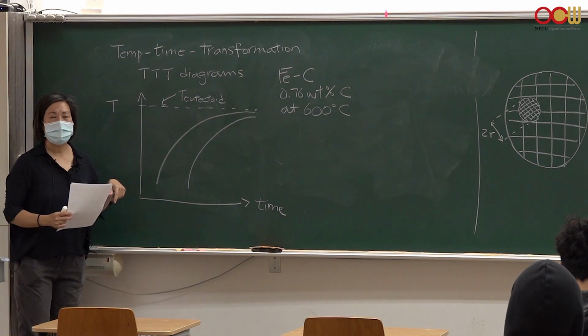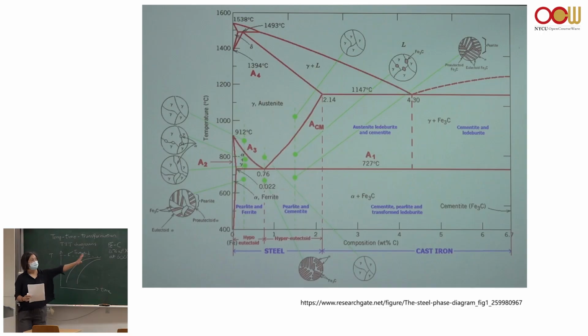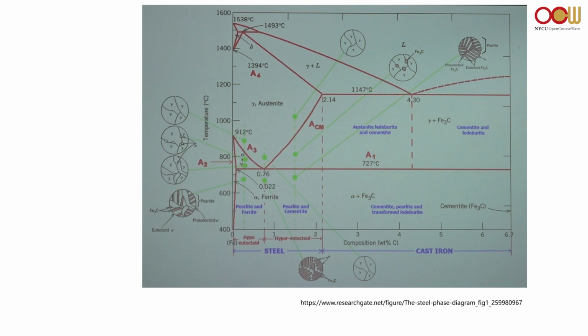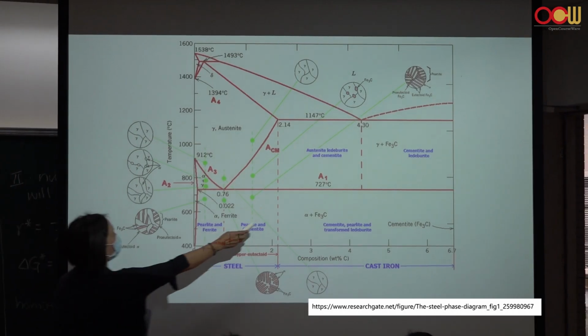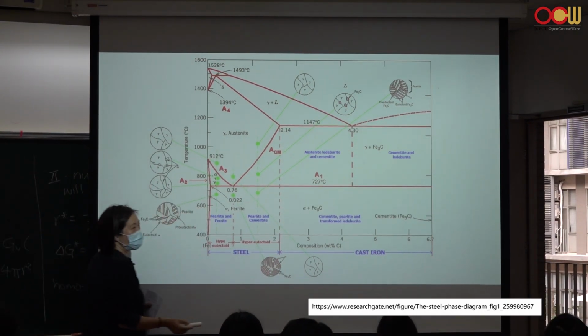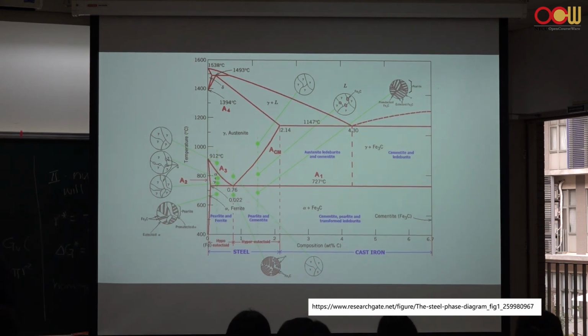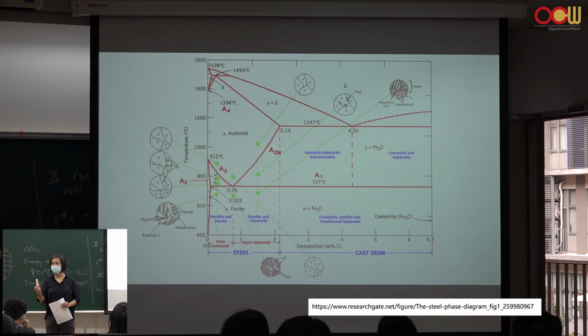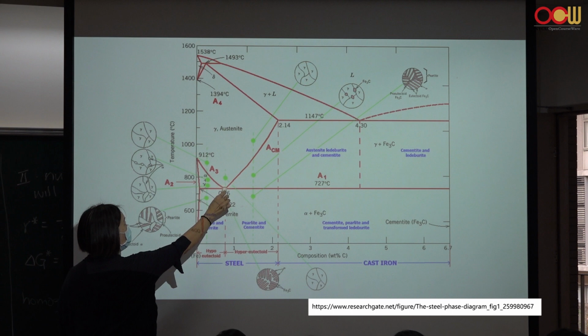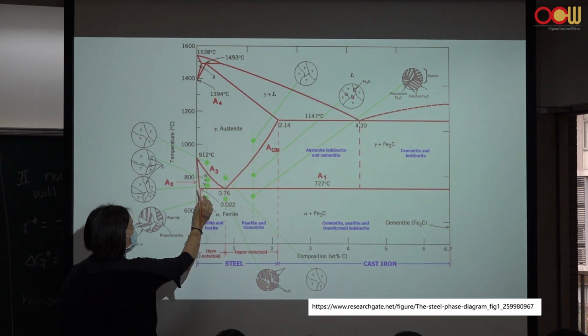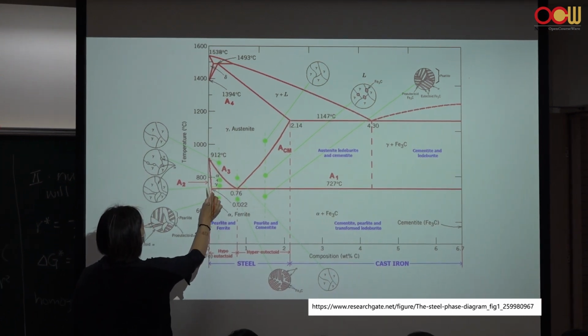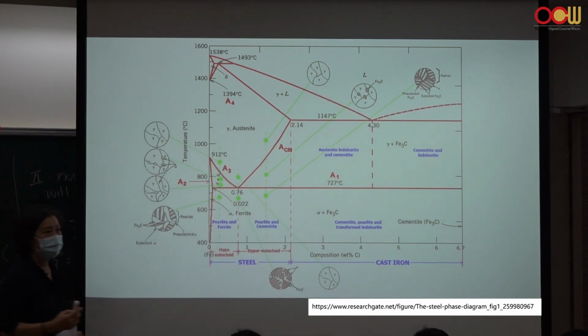So what is my eutectoid temperature? It's on the phase diagram. Yep, close to 720, right? It actually tells you here, 727. Eutectoid is when one solid phase, under the same concentration, when you lower the temperature, becomes two new solid phases. So the eutectoid point is here, and the temperature is right here, and they tell you it's 727.